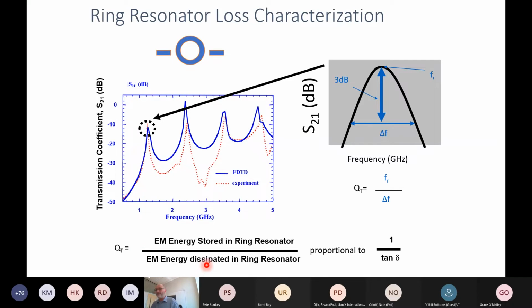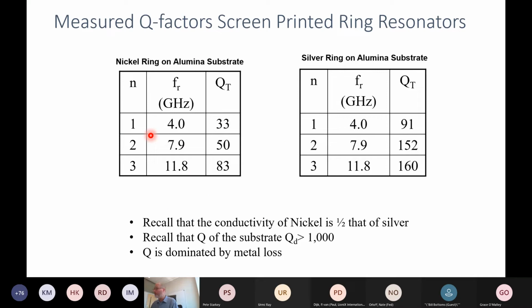Okay, so we now have a device measurement. We've measured our ring resonator. We have the same dielectric substrate, the aluminum oxide substrate with a very high Q value. And let's go ahead and look at the results for these two different metals. So you'll note here we actually did the first three harmonics, n equal 1, n equal 2, n equal 3. We compared the nickel ring and the silver ring, both on the same substrates. And here we can see the Q values.